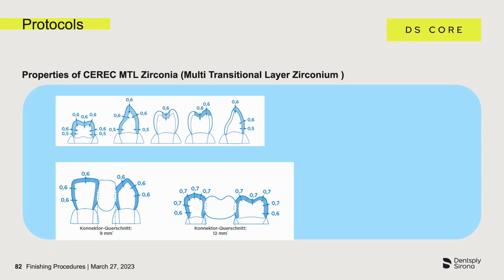Here you can see once again in detail how thick the minimum wall thickness may be for MTL zirconia restorations. This is generally 0.6 millimeter occlusally. Posterior bridges should have an occlusal minimum layer thickness of 0.7 millimeter. Both apply provided that the restoration is adhesively luted. The connector cross sections for bridges in the anterior region may be 9 square millimeters. For bridges in the posterior region, this should be 12 square millimeters.